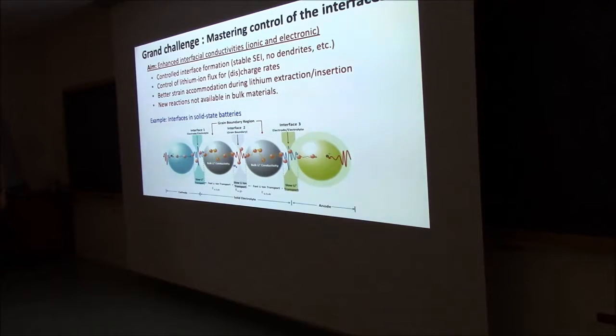And maybe at these interfaces, maybe you can do something which normally is not available if you do more bulk processing. And if we think about solid-state batteries, within each component you have a lot of grain boundaries, but the most important is if you go from cathode to electrolyte to anode, what can you do there at the interfaces to maybe align the crystal structures so the lithium ion can move. Let's say if you have a layered structure, it moves much better within the layer than across the layer. So if you can control that, you can improve this.